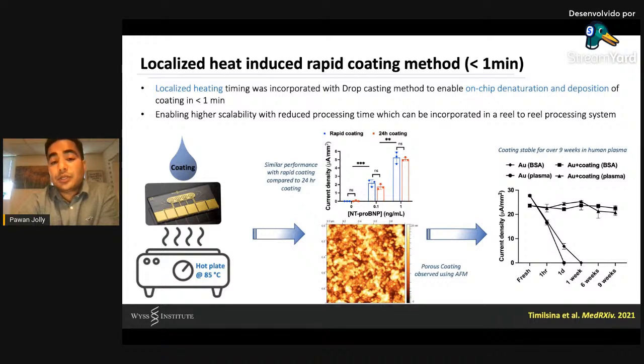But what happens to the electrochemical behavior? If you look at the performance of our rapid coating versus the 24-hour coating, we didn't see any difference when we performed the assay. When we looked at the AFM image, we were again able to demonstrate the same porous nature of the coating. Using this rapid coating, we challenged our sensors even up to 9 weeks. Last time we showed you 1 month, and this is for 9 weeks. In plasma, we were still able to retain most of the conductivity and it did not lose that much sensitivity. So it really enhanced the properties even further.